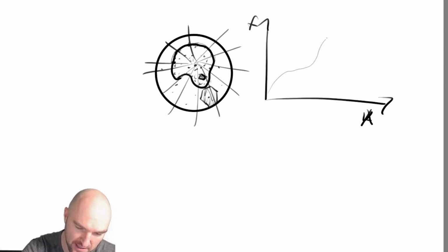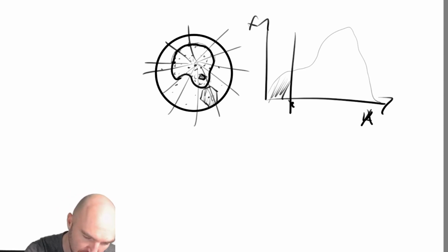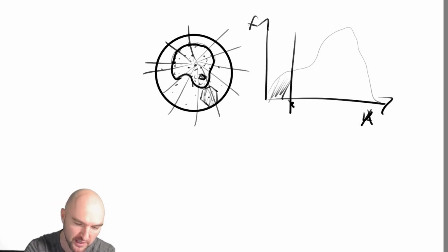And then it gets some kind of histogram, whatever that looks like, and it says, okay, here we've got the bottom 5%, and I'm going to take out the bottom 5%, which is hopefully all of the hits out here, but probably also some in here, which doesn't matter because our alpha hull still will give us the correct result if we take some of the atoms in here out. That may be because they're close to a pole, they may have a small area around them, or for whatever other reason.